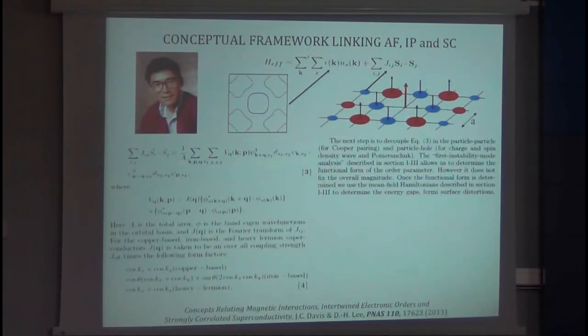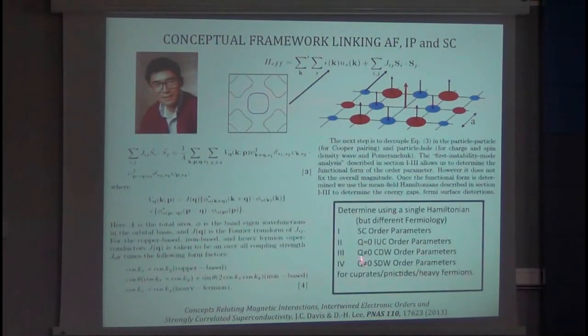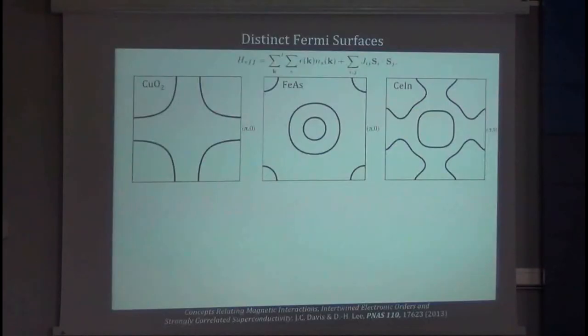You can find out which superconducting order parameter will exist, which charge density wave order parameter will exist, which nematic order parameter will exist. It's a very well-defined theoretical idea, which has existed for decades. So Donghai carried out that calculation to figure out what are the different order parameters of every type coming from this quantitative Hamiltonian. And so he figured out the superconducting, the nematic, and the charge density wave order parameters for each of these types of compounds.